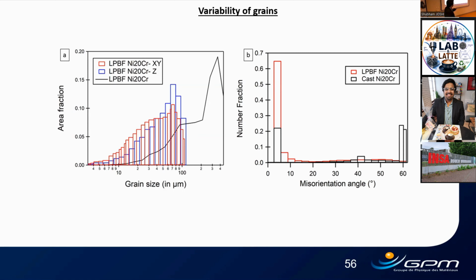The first LPBF in building direction and the cross section to see the area fractions of grain sizes in different axes. So we can try to see if we have a morphological texture and if there is an average. So for other samples, also what we have done is we take an average or the highest area fraction for grain size for one axis, and then we take another axis higher, and then we take an average. So it's a bit crude method.